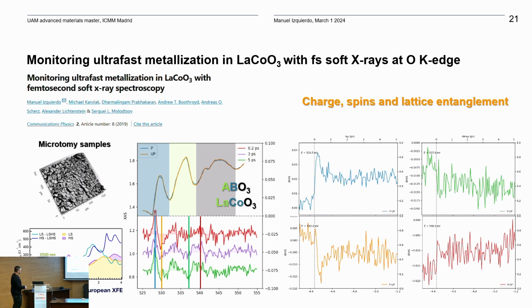We also want to give a twist. The first experiments were done at 800 nanometers, where you excite LCO above the gap. In this case, what we wanted to see is how the dynamics change when you excite with 2.5 microns, that is well below the gap. And so these are the results. The data analysis is ongoing, but what we can see is a little bit what we have observed at 800 nanometers.